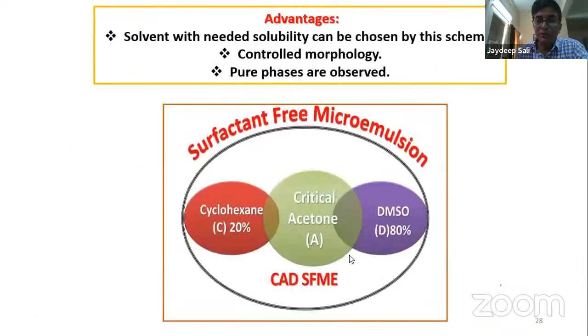Okay, so the microemulsion that we worked with was this. We use cyclohexane as a solvent for the organic compound, that is ICBA. We use DMSO as a solvent for perovskite, and we mix acetone in this solvent mixture, which stabilizes the microemulsion. So here the acetone is not acting as a surfactant, but it is mixing with the cyclohexane as well as DMSO and stabilizing the microemulsion. So remember, DMSO is a solvent for perovskite. Cyclohexane is a solvent for the second, organic component, and both are immiscible.